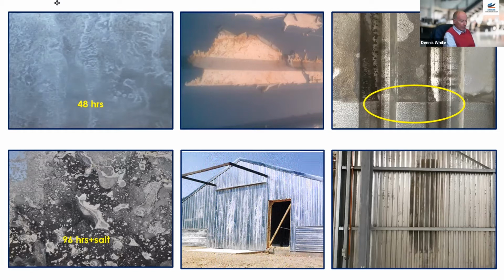So with a zinc surface, you'll get that white residue that you see in that middle photograph on the bottom there. And when it comes to aluminium and aluminium zinc alloys, you get a black stain. And once you've got to that black stain state, that material is damaged permanently. It might not have damaged the coating to the extent that it would fail, but the black stain you cannot wash off or clean off.